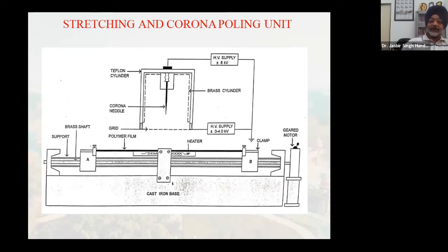And it has been found that simultaneously stretched and corona poled films give very good results in some of the polymers. Though for me, simultaneous stretching and corona poling didn't help much. It was only stretching and poling, or heating and poling that helped. But in case of polyvinyl chloride, there was a research scholar who worked, and in that case, he was able to get results with simultaneous stretching and corona poling. So it is like heating a cold film, heating a stretched film, heating and poling a stretched film, or heating and at the same time corona poling. So these are the different things which we do.